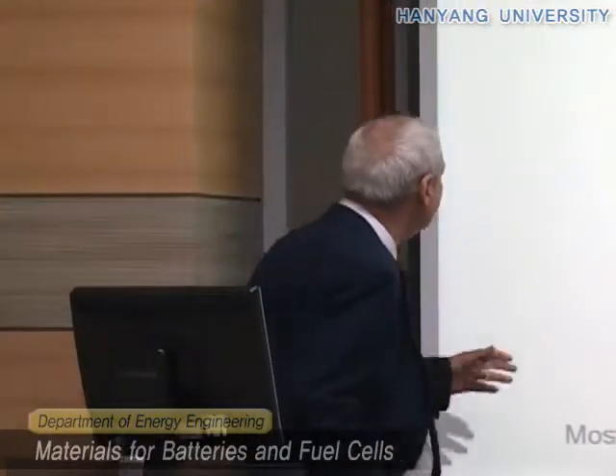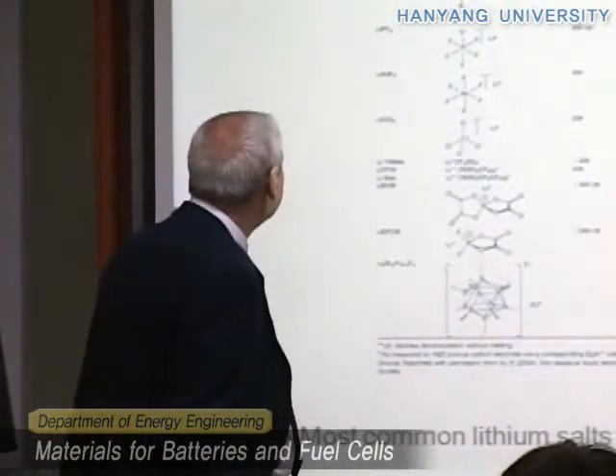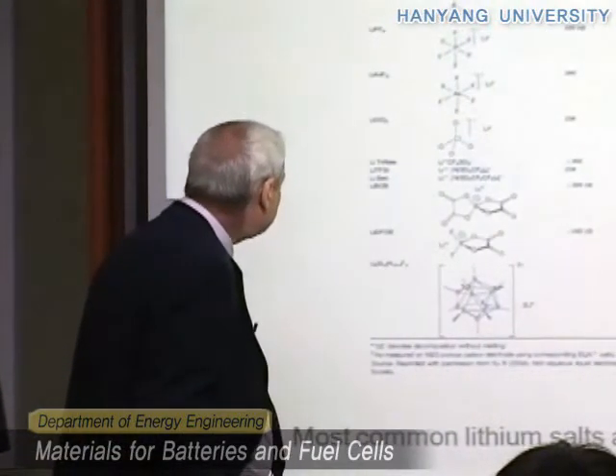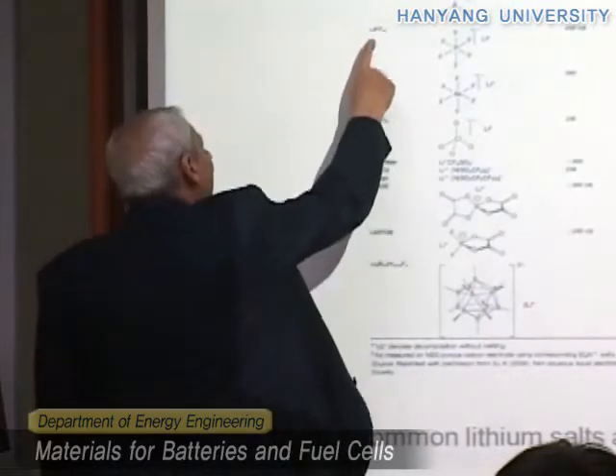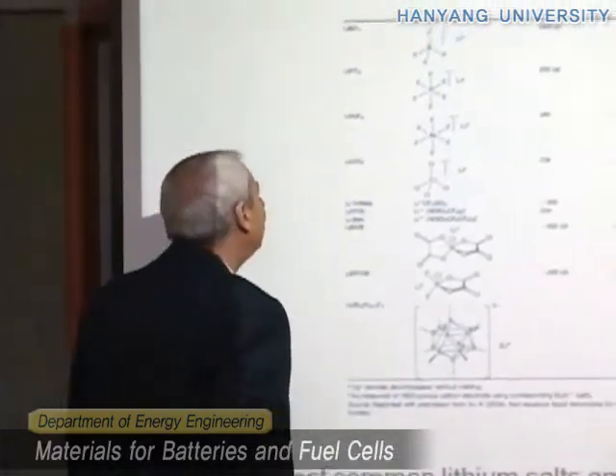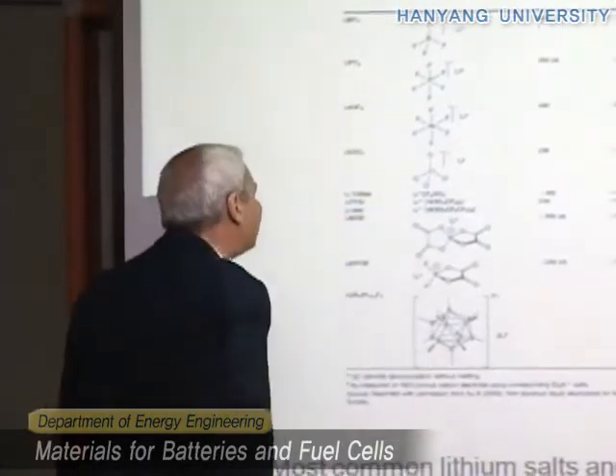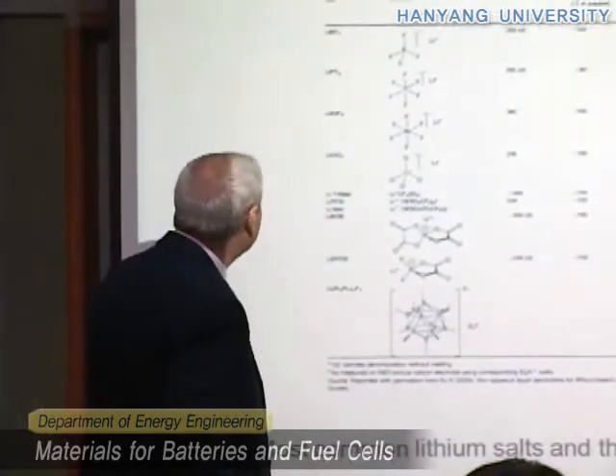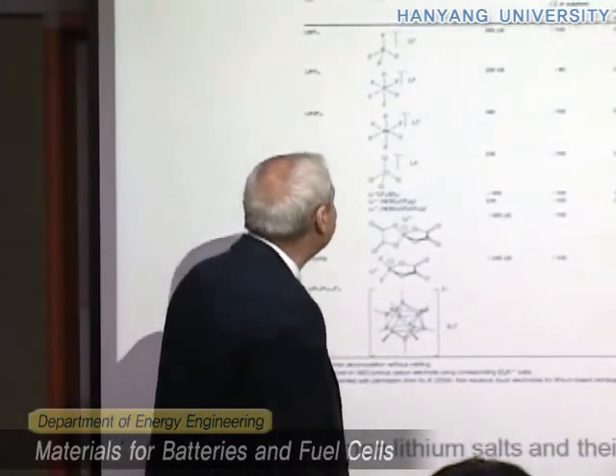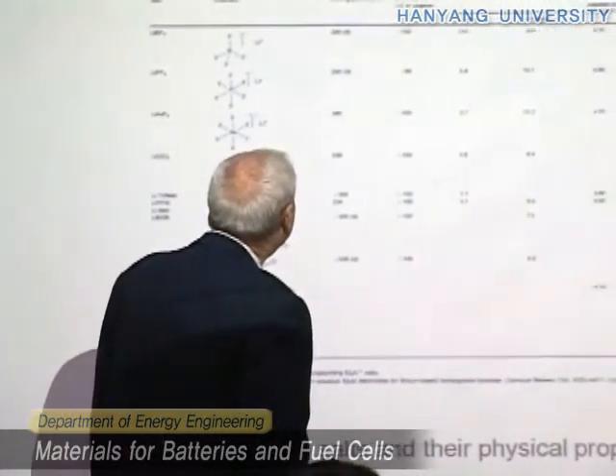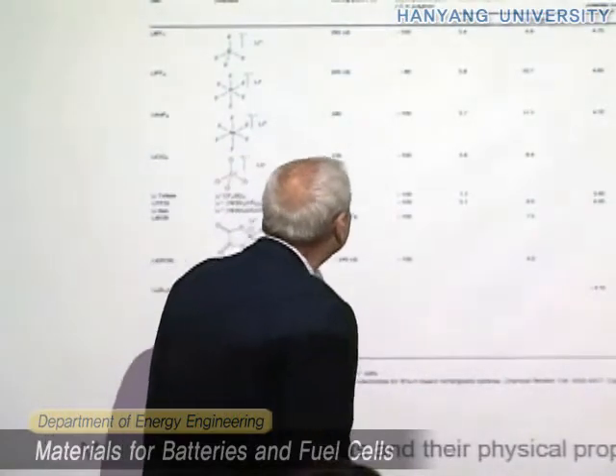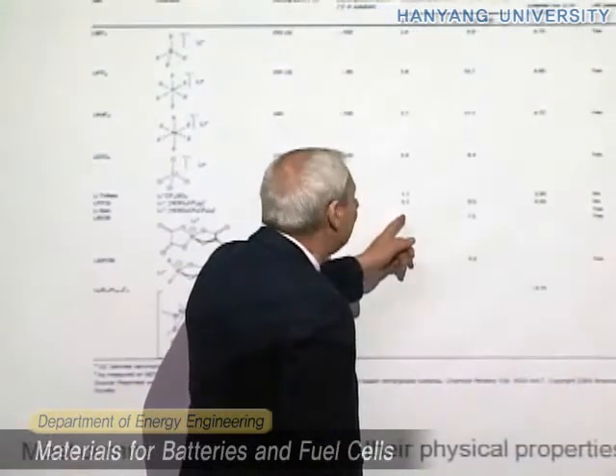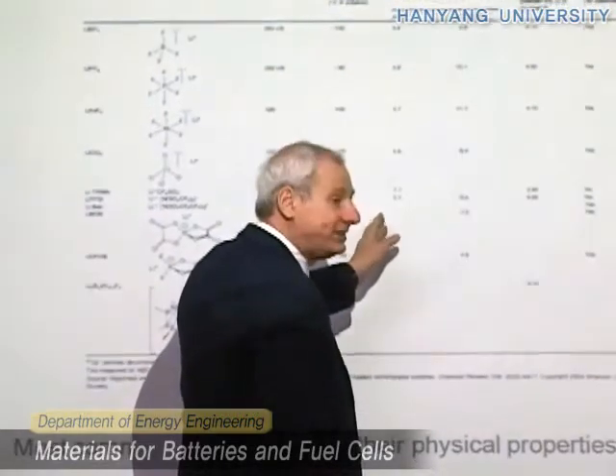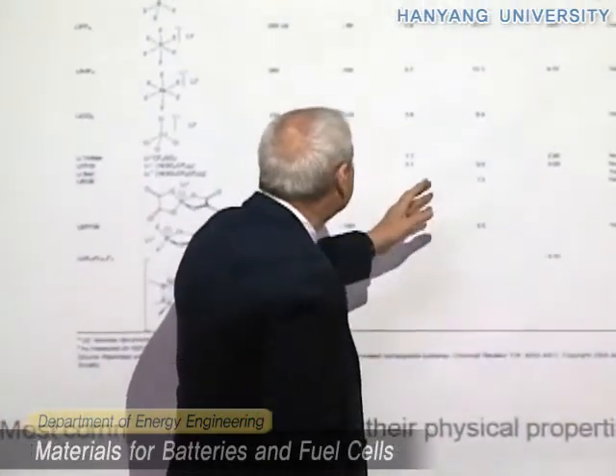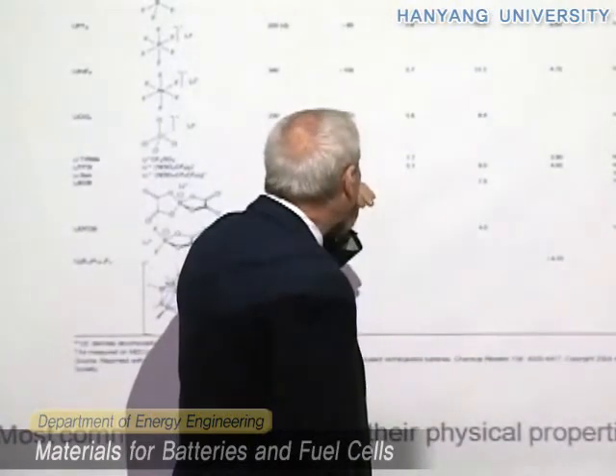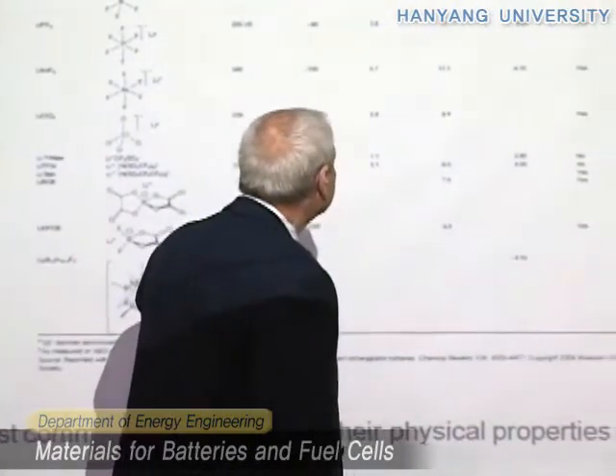Here you see the various salts that we can use, okay? I think this one should be LiBF4, and this is the most common one, LiPF6, and others. And you see the most interesting property is the conductivity. Here are the conductivities of these salts, to the left in PC, propylene carbonate, and to the right in the most common solution, which is EC, ethylene carbonate, and DMC.